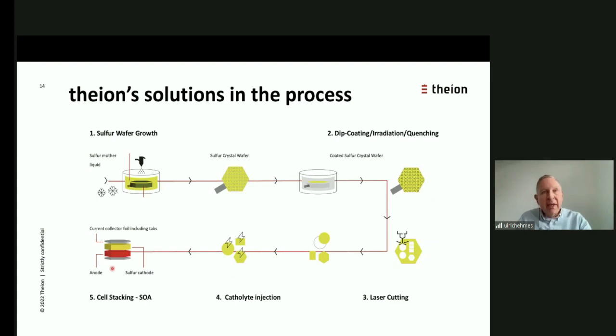The last step, and from now on it's state of the art, is the stacking process. We add a lithium metal anode together with our sulfur crystal cathode. And these monocells are then stacked to the number of layers we need for the application. So it's 4 to 8 layers in a small pouch cell for portable cell phones, or up to 40 layers, 40 monocells, in a pouch cell or hard case prismatic cells for EV applications or flight applications.